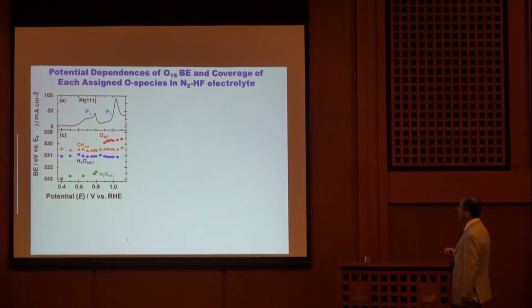Here shows the potential dependence of the O1s binding energy and coverage of each assigned O species in nitrogen saturated HF electrolyte solution.